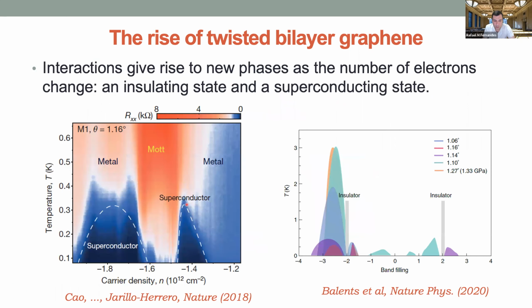So the group of Pablo Jarillo-Herrero, in this again very influential paper in 2018, showed that indeed if you twist bilayer graphene at this magic angle, you see a correlated phase, an insulating phase near half filling, followed by two superconducting domes. So this is the first observation of a superconducting phase in a graphene-like system that is not induced by a dopant.